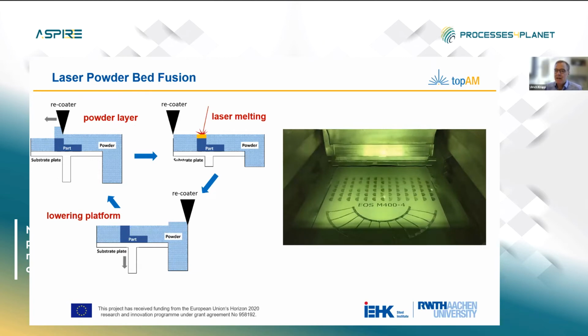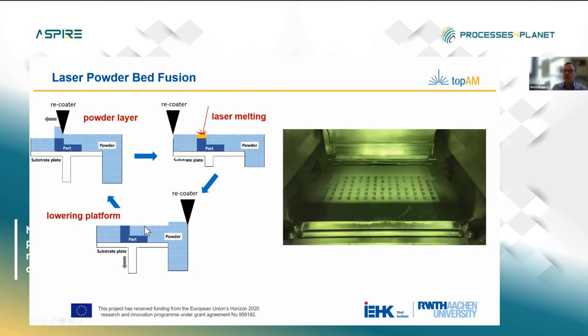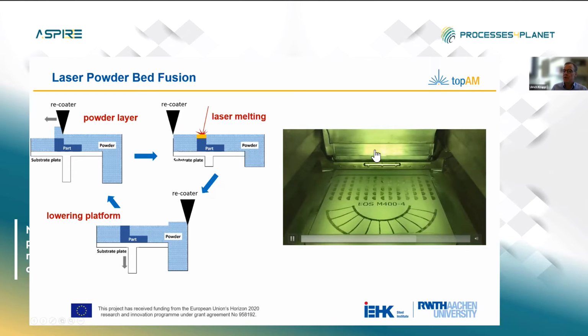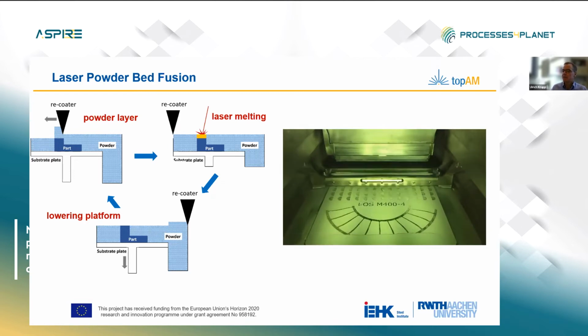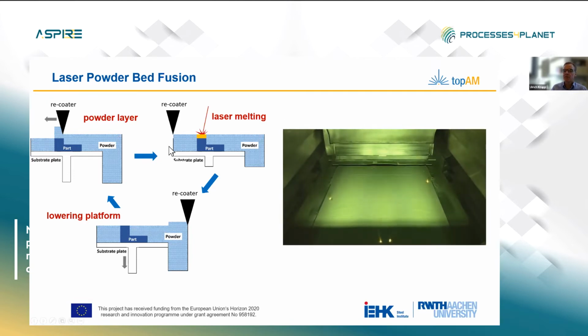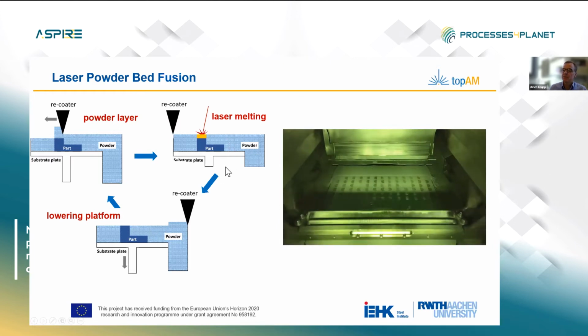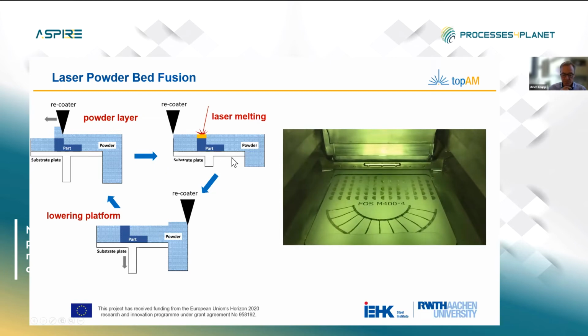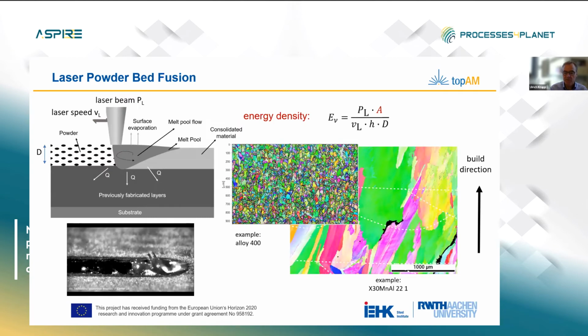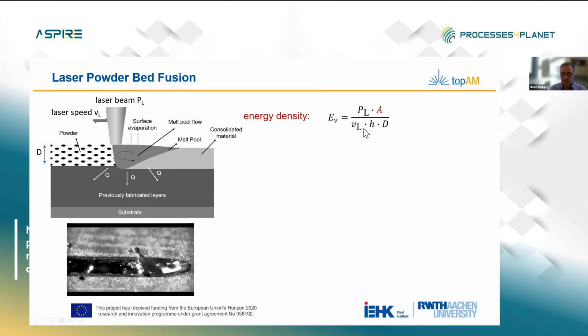The next step is laser powder bed fusion. Here we do a two-dimensional laser melting of the powder bed. Then the build platform is lowered, and a recoater applies new powder, which you can see here in the video. Then the process starts again with the laser melting, and the component is constructed by layer-wise laser melting. Finally, you have to remove the remaining powder, and the part needs to be removed from the building platform. The main parameters are the laser power, the velocity, layer thickness, hatch distance, and the absorption of the laser beam.